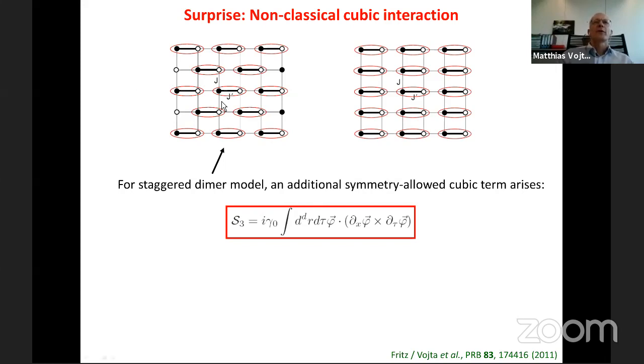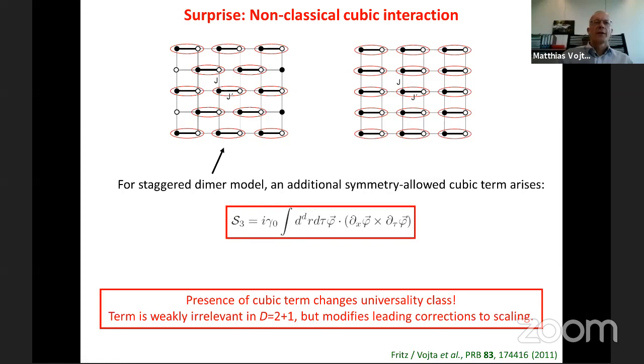But for this system here on the left-hand side, it was found out that it's different, and we set out to understand this, and it turned out that here the field theory admits an additional cubic term, which usually is forbidden in all the other systems. That's a term which involves three powers of the order parameter, and then there are a few derivatives to make it compatible with global symmetries. And upon analyzing this term, one can figure out that it indeed changes the universality class of the transition.